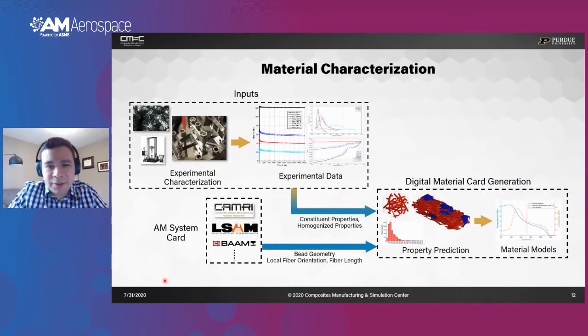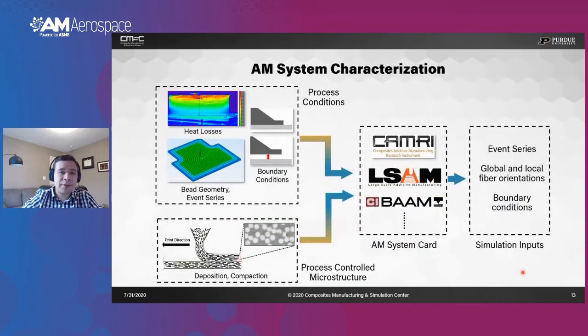So going a little bit into the details of the material inputs that we need to create the digital material card, we combine both experimental characterization with virtual characterization to generate the inputs for different material models that we use in our physics-based simulation workflow. And in terms of the system card, we also need to consider the different conditions developed inside the printers. For example, how the part is attached to the substrate, the heat losses developed inside, how the bead deposition strategy is performed, and how that affects the fiber orientation distribution within the bead.